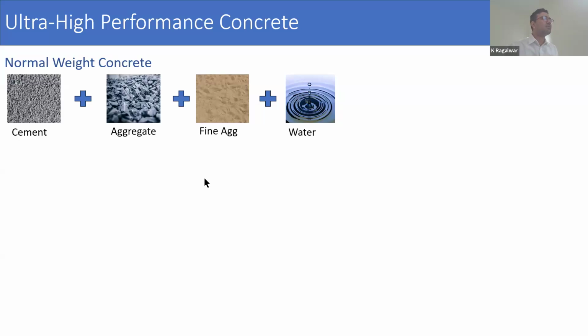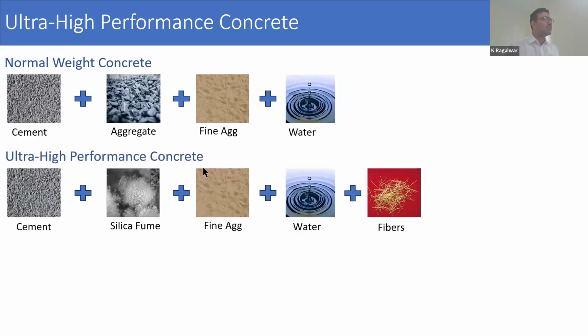In the 1970s, there was development of high strength concrete and also self-consolidating concrete, which further led to the understanding that concrete gains its strength from the aggregates which are bound together by the cement paste. So the concrete strength is usually as good as the strength of the cement paste and the inherent flaw. So what do I mean by inherent flaw? If we look at the fracture-based model for concrete, we observe that basically concrete paste binds the aggregate together. But the larger the aggregate, larger is the flaw size. So that flaw size determines at what stress we see the initiation of failure in concrete. Okay. So if we keep on reducing the flaw size, then we see higher strengths.